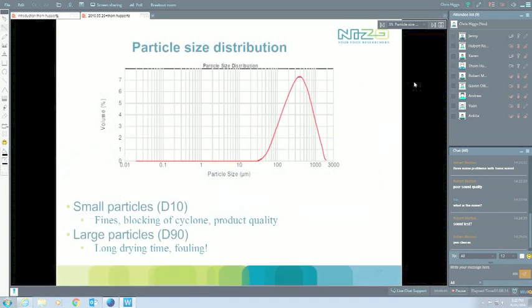So as we said earlier, it's really about controlling the particle size distribution, so make sure that we avoid the very small particles, because they will be blocking the cyclones, they will have big effects on product properties. We should also avoid the very large ones, because they will really give us long drying times, high heat load on the product, a lot of fouling there, and a lot of issues from that aspect.